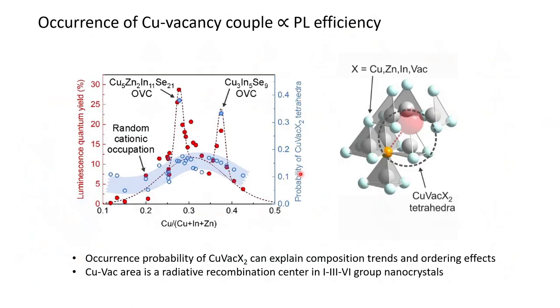And so what we learn from this, assuming the random cationic sublattice, is that we can match some of the occurrence probabilities with the quantum yield directly. So this shaded area here is a random cationic occupancy. It's the probability of a small structural unit which has copper and vacancy in its structure, a copper vacancy couple, let's call it this way. And it can explain the background feature for the efficiency of luminescence, light coming out. What's even more intriguing is that some compositions we can order. And with that we increase the probability of these copper vacancy couples.